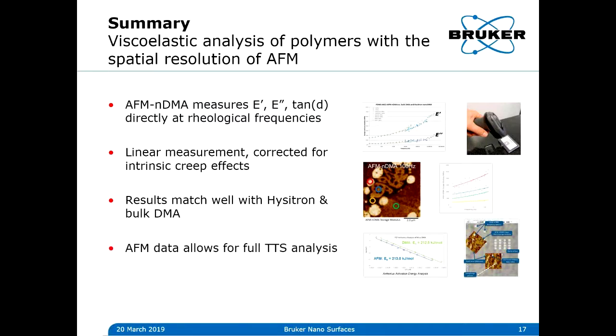Since the AFM-nDMA works at well-defined frequencies and temperatures, it is possible to generate master curves using the time-temperature superposition, as well as doing the Arrhenius or WLF analysis with the resulting shift factors. And then finally, AFM brings the possibility of doing the measurements with the resolution of better than 50 nanometers. And that really gives you the possibility of doing something you couldn't have done with a bulk DMA machine or Instron, and that is to understand the influence of the microstructure on mechanical properties of materials.